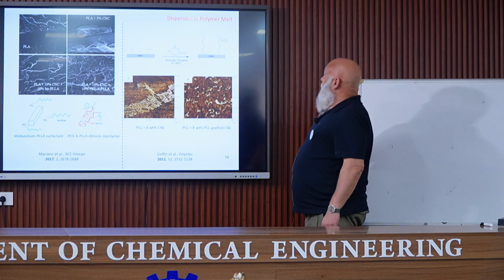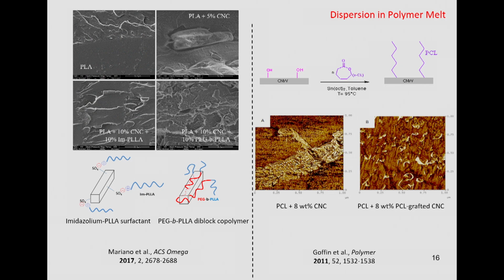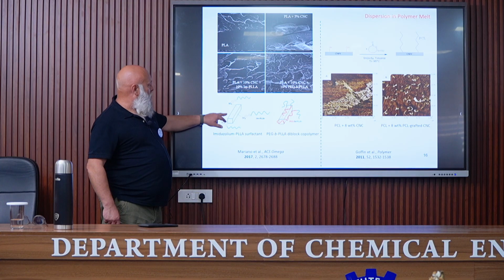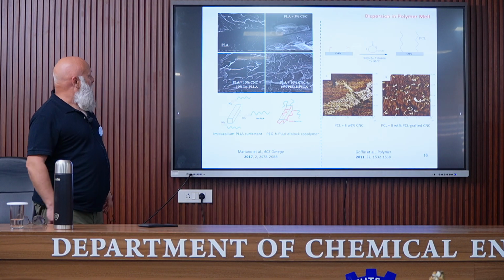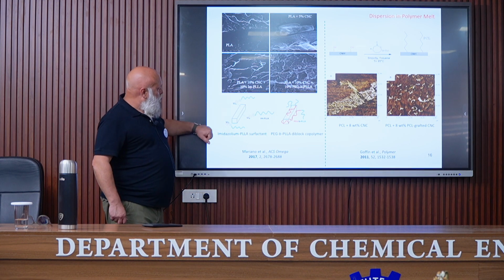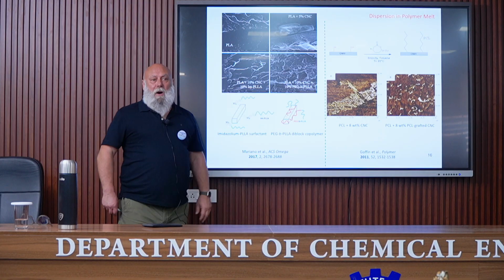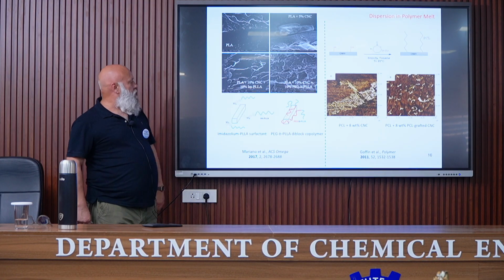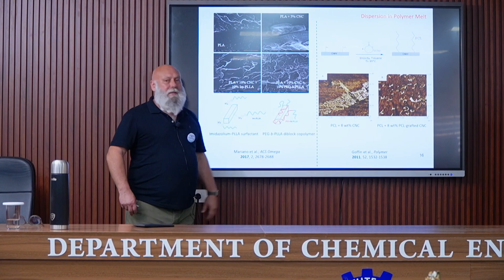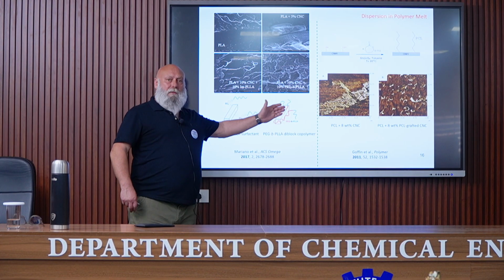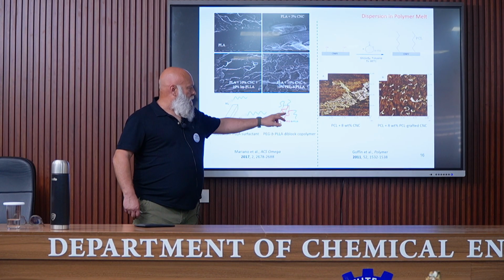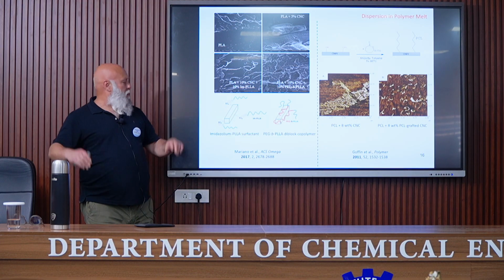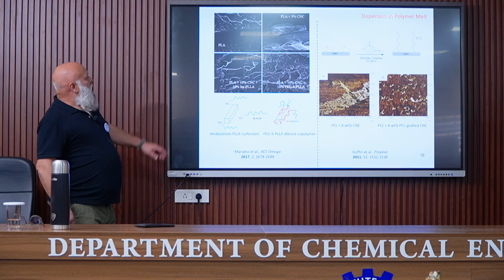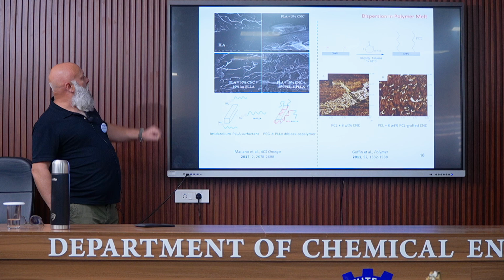These are some other examples in which compatibilization was performed, in this case using imidazolium PLLA surfactant, so with a positive charge here that can interact with the sulfate groups from the surface of the nanocrystals, and this part, which is PLA, because the matrix that was used was PLA. Another example is a diblock copolymer of polyethylene glycol that can interact with the OH group from the surface of the nanocrystals, and PLA that will interact with the matrix. We can see the impact on this SEM micrograph.